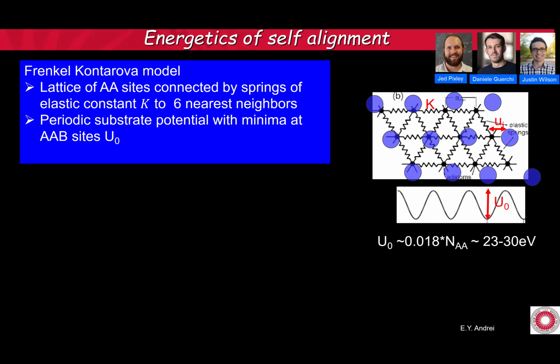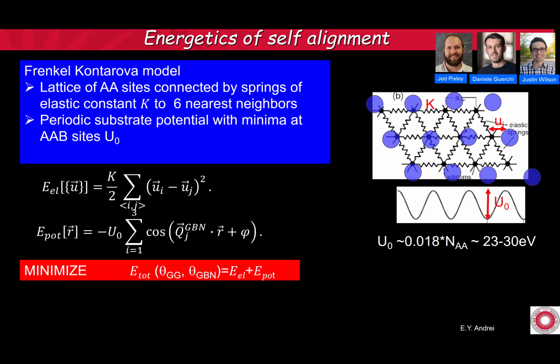So here is a simple model from our theory collaborators. This is a Frenkel-Kontorova model. So they model the AA sites by masses and the elastic energy in between them by springs, and they put it in a periodic potential, with the height U naught basically the van der Waals energy in a moiré, and then they can just minimize the energy. You can calculate the elastic energy, which comes from how far you are from the equilibrium position, and you calculate the potential energy here, and then you minimize the energy, and then you see what happens.